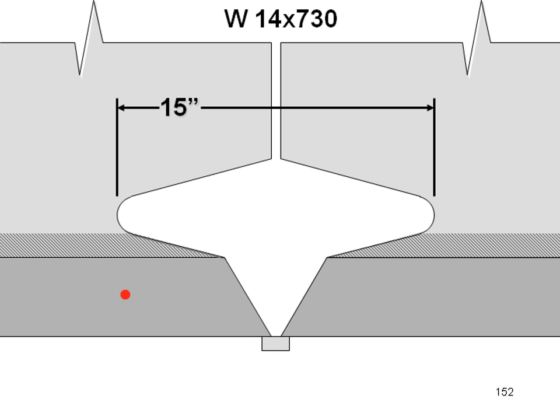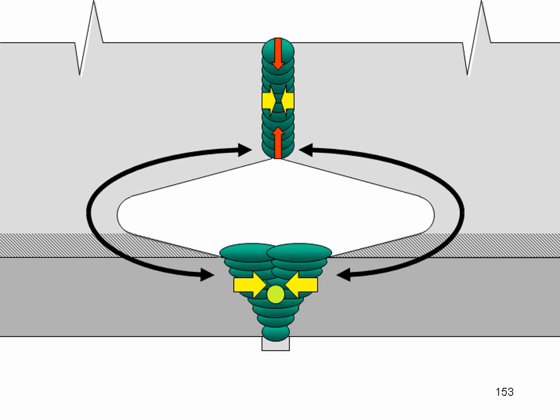Now that sounds huge, and it is quite large, but with 15 inches, there's no way that the residual stresses of the web weld interact with the residual stresses of the flange weld. In contrast, here's the weld access hole from Orlando. And you see it's been supplied. It's just big enough to get access for welding. That's it. Now, there's a few other things that we can do to minimize the stress.